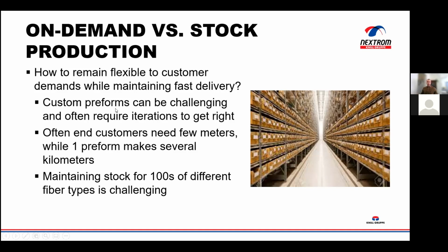Making custom fiber is a challenge because first you have to define the type of fiber that's required. You have to design the preform, the dopants, and you don't always get that right on the first try. So you may be required to make multiple preforms for this one fiber that the customer may only need a few meters of. An average preform may take 8 hours to produce, to deposit the glass, then some more time to collapse the preform, then you have to draw it. And if the customer only needs a few meters, those few meters are going to be extremely expensive unless you can sell the rest of the fiber, which you're not sure about.